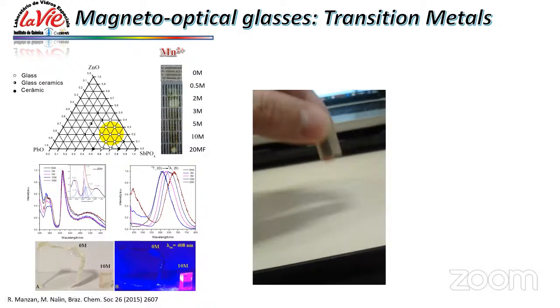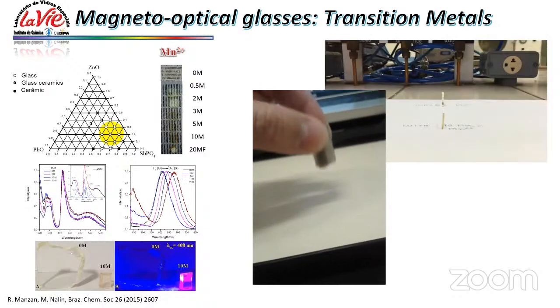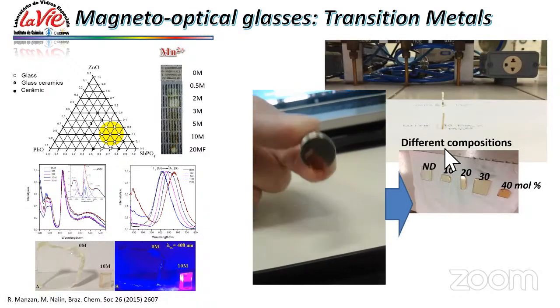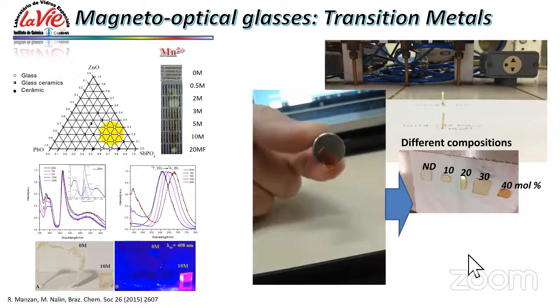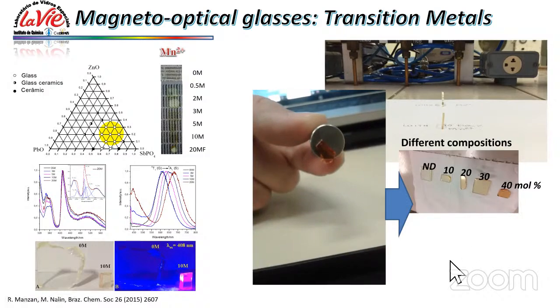After that, we changed the composition of the glass, we increased the amount of manganese, and then we can find glass with a much stronger attraction to the magnet now. So now we are studying the magneto-optical properties of these materials.